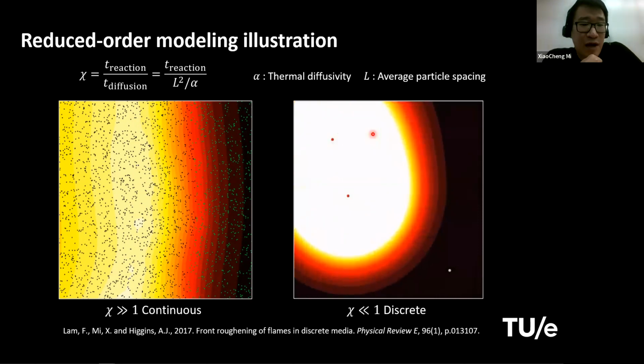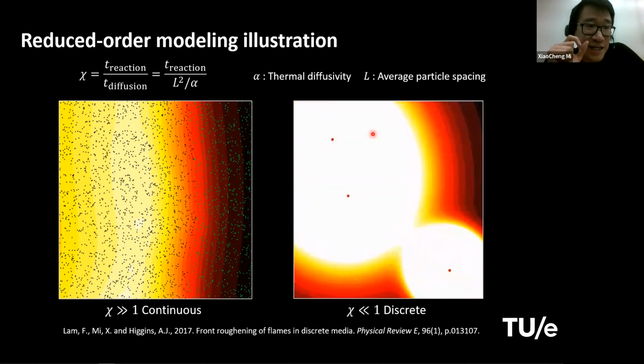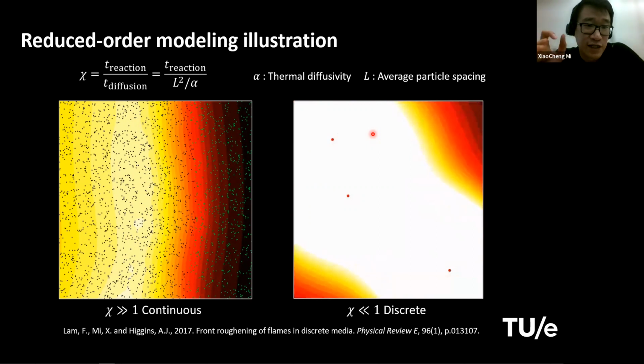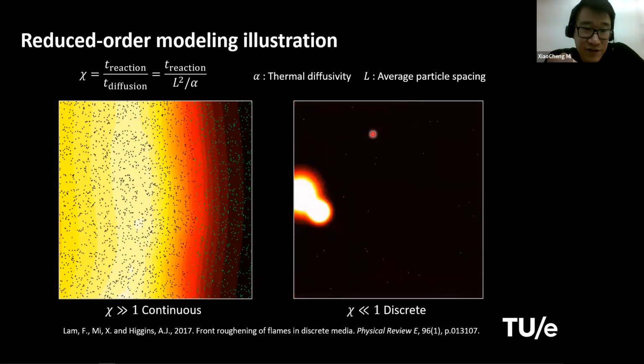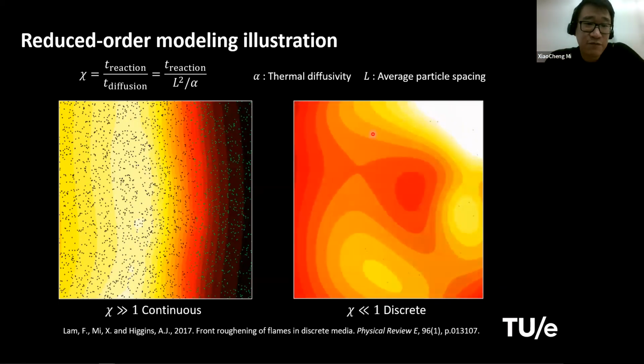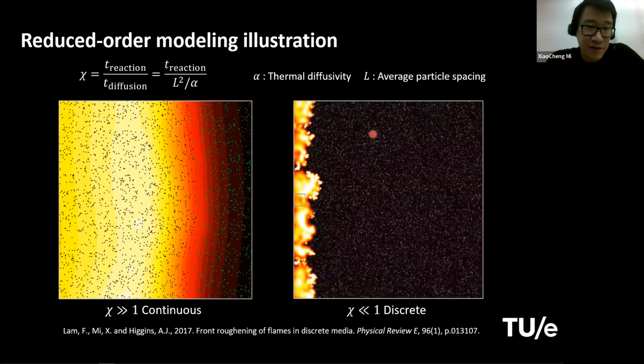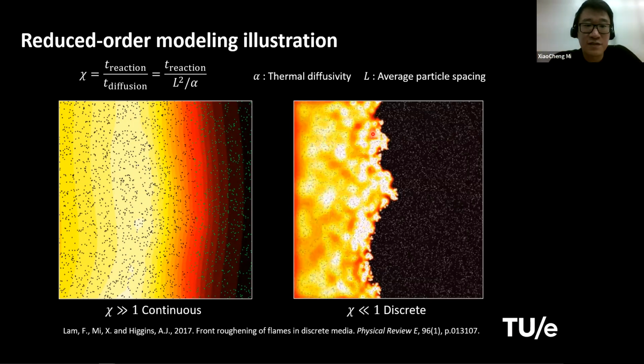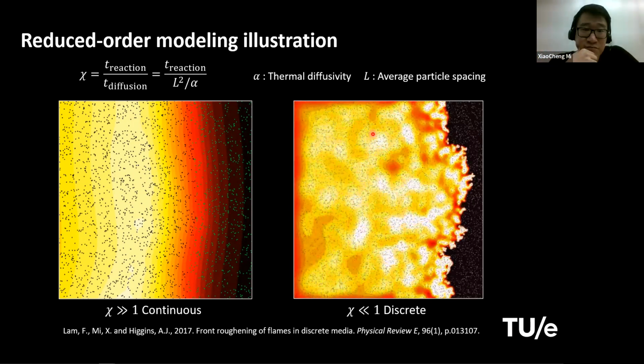But if this chi parameter is much smaller than 1, that means your reaction time is much smaller than interparticle diffusion time. And after each particle releases heat, it takes time for the heat from one particle to reach its neighbor. And then the resulting flame is totally different. It gives you this highly non-planar flame front and with all these finer details between the particles. So these are only theoretical pictures. Like what really happens in real world iron dust flames? Is it something in between or something even more complex?